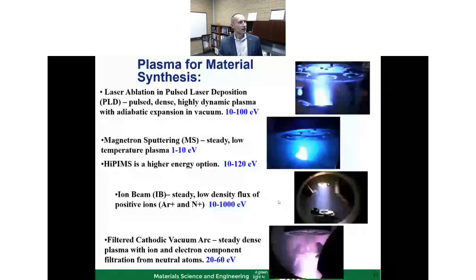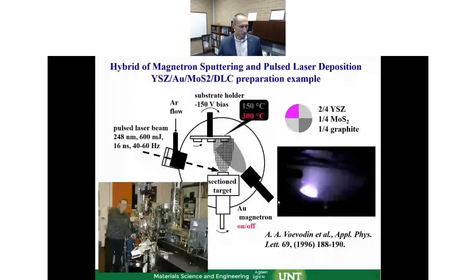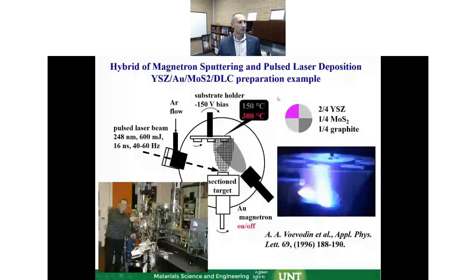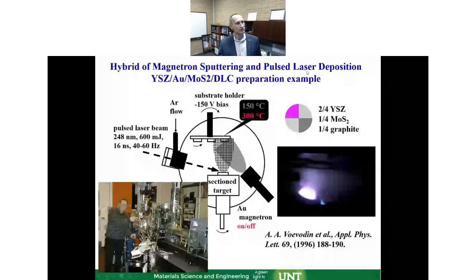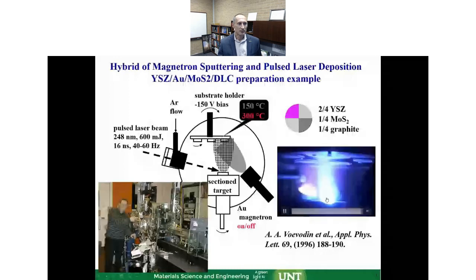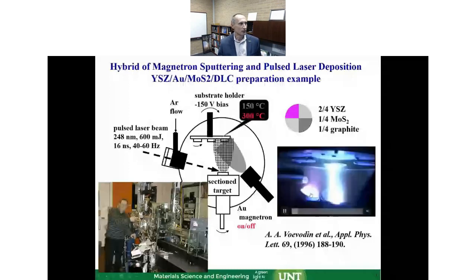All right, so that moves me on here. We want to combine this, and one example which I've worked on before is a combination of, in this example, sputtering and pulsed laser deposition. You see the movie coming here, the laser striking on the bottom, and the plume is coming up, and the sputtering is on the sides. Out of this arrangement, we have a combination of relatively high energy flux coming off the target, and the target is zirconium oxide, molybdenum disulfide, and graphite, and then relatively low energy flux coming from the magnetron. In this case, it's providing gold as a component of this coating.